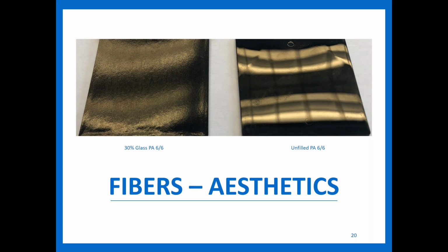So if you're looking at something where the aesthetics are absolutely important, it's going to be a huge deal breaker. It's something you might have to look at if you need to move to a glass-filled grade because of the mechanical and thermal performance you get from it. The other thing to note here is I don't have a picture of mineral-filled or filler-filled material compared to the normal. It will affect the appearance as well a little bit, but it will not be as drastic as the fibers. So if aesthetics are more important, potentially a filler could be used. I wanted to point that out.